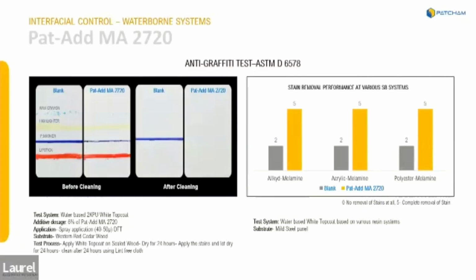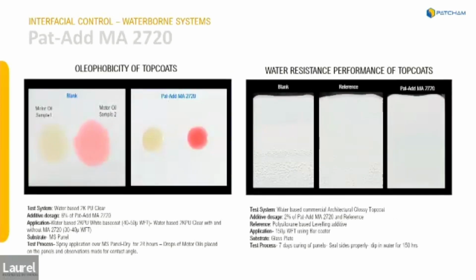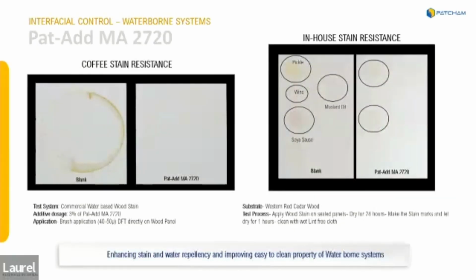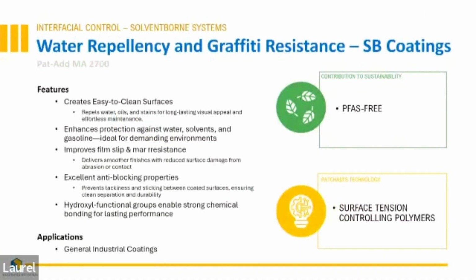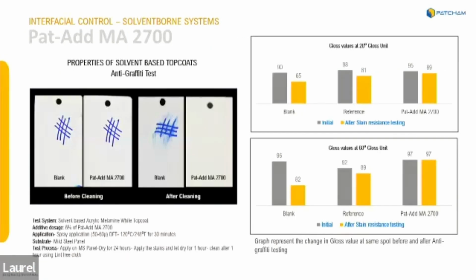These materials will not migrate because they cross-link into the system as a part of the binder. So each layer, there's the same level at the surface. And they provide then dirt release, stain repelling properties to the coating. And we're going to see the evidence of some of these. For solvent-borne as well. These are the solvent-borne examples.